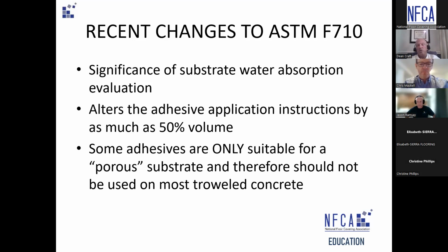I was involved with a 200,000 square foot project where the project specs had selected adhesive as recommended by the manufacturer. I was the only one to go to that manufacturer's literature, and the only 2 adhesives they recommended were only for porous substrates. So I alerted the project, saying, you might be looking at a $700,000 change order, because it says if non-porous, bead blast, self level, just to change the glues. That's assuming the underlayment will be porous, which is a flawed assumption. So you could have gone through bead blasting and self-leveling just to get back to another non-porous surface. So instead, they just pick a different glue.